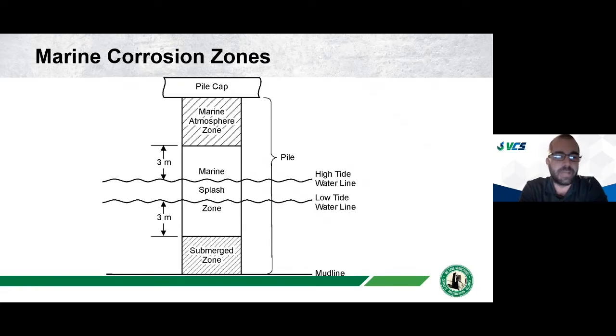So, kind of being cognizant of that situation in the marine. The marine atmospheric zone is when you're near the beach and you can smell the salt air. That's what the marine atmospheric zone is. Salt and moisture are in the air. They can deposit on structures, on concrete structures. The chlorides will then migrate into the concrete and cause corrosion of the steel. So the marine atmospheric zone, again, not as aggressive as the marine splash zone, but a very real and very corrosive environment as well.